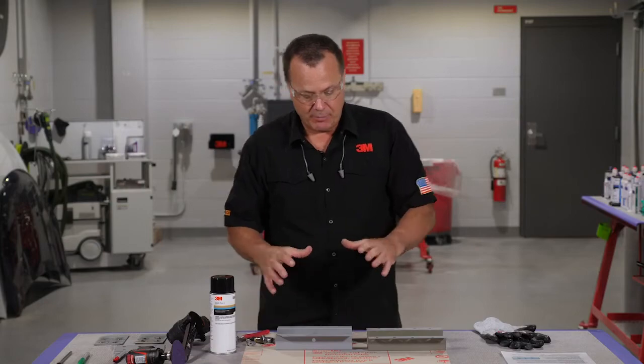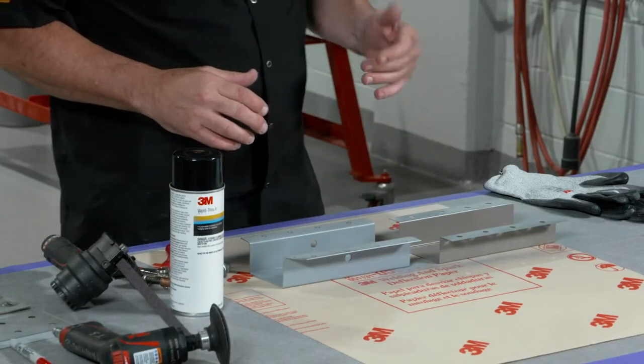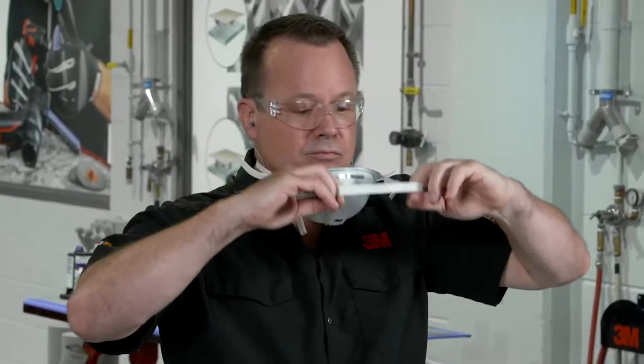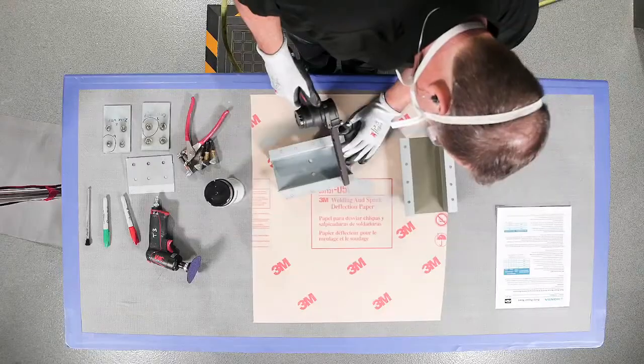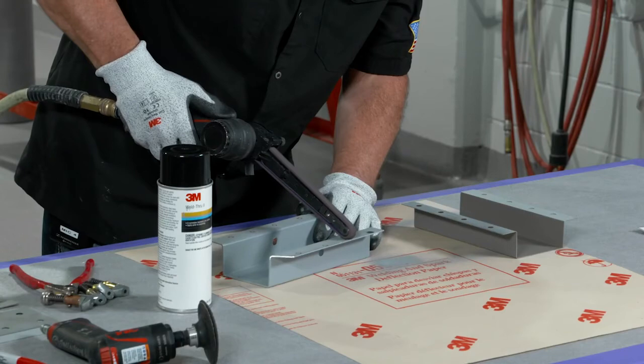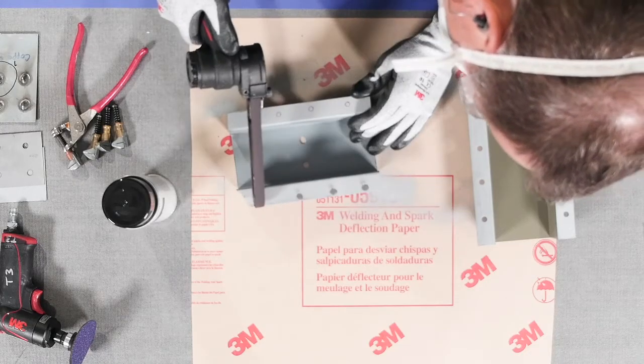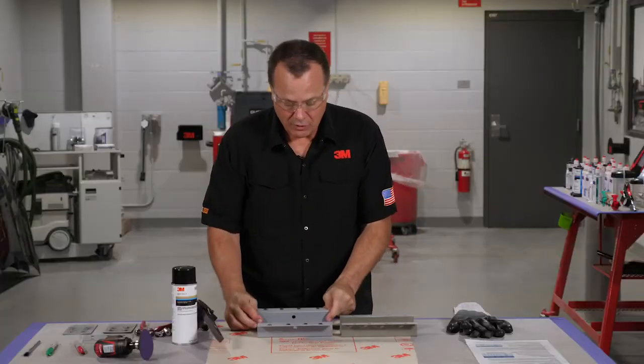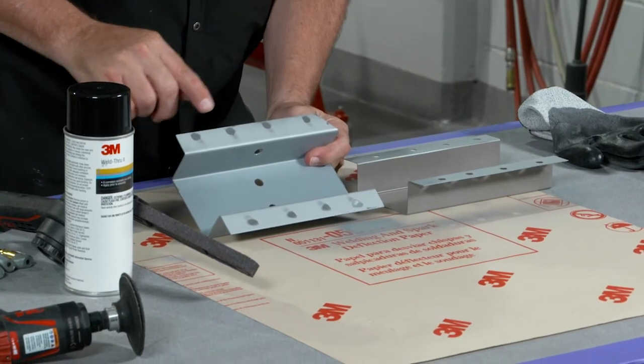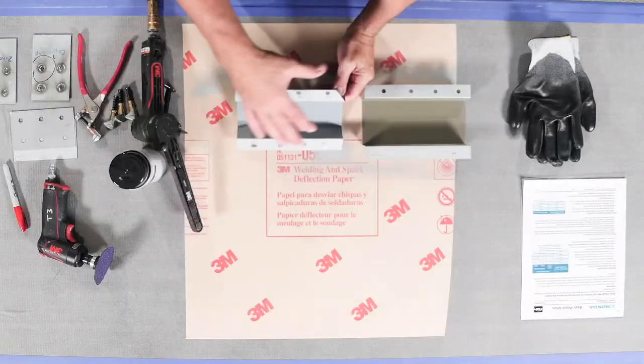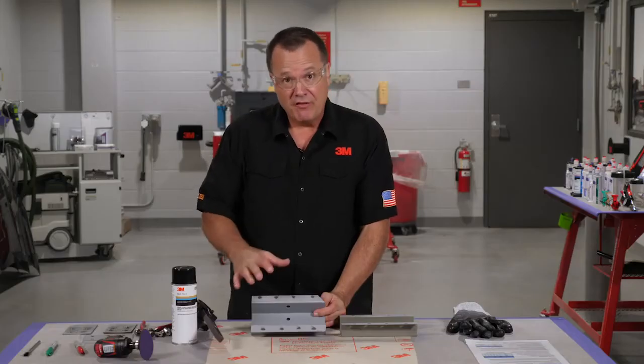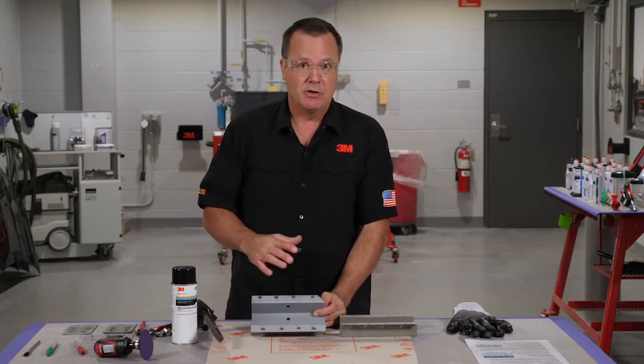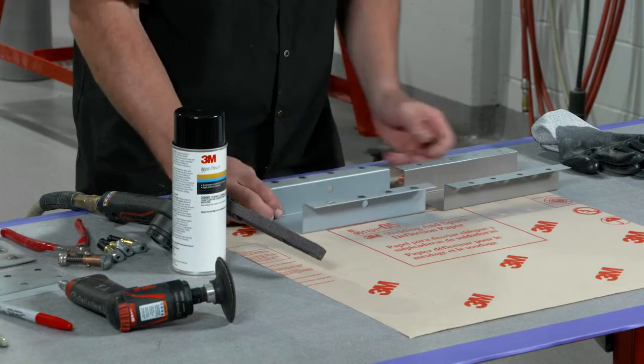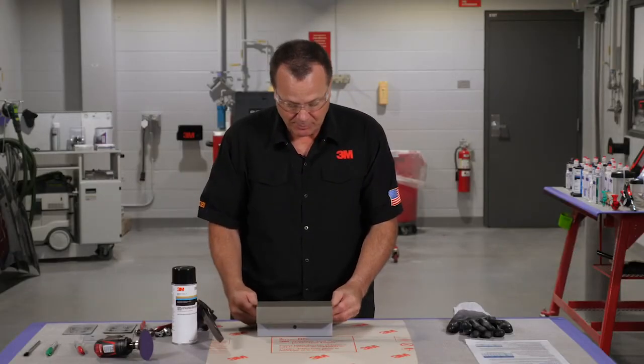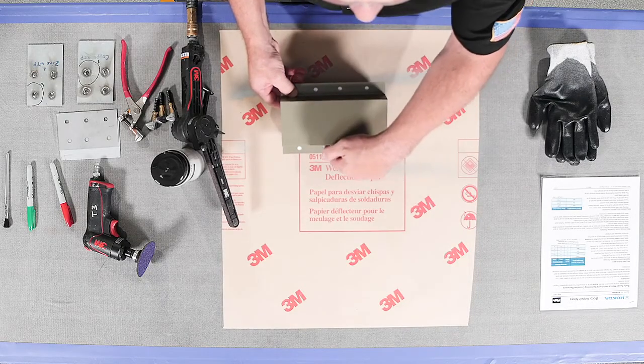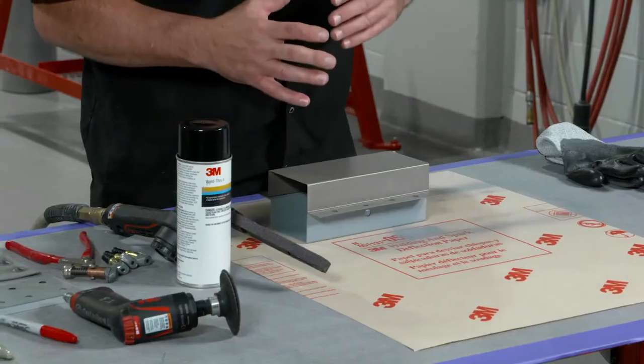So I'm going to get on my safety equipment and grind off these areas where I want the primer removed. As you can see now, I've simply removed the primer just from these specific weld spots, which isn't going to sacrifice corrosion protection at all, but it will definitely make it much easier to weld when you're welding on clean steel versus attempting to weld through a coating. So once I mate these back together and clamp them in place, I can see nice, clean, bare steel in these areas, and it's going to make for a much more successful repair.